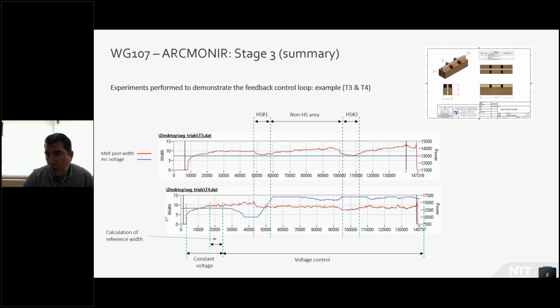However, if we introduce the voltage control and the closed loop control system for the arc voltage, we can see that in the area where the first heatsink starts, the melt pool goes to around the initial value here, which is around 9.5 millimeters. And then we can see that during the whole rest of the process, the melt pool is quite constant. And when we get to the second heatsink, it goes down a little bit again, but not as much as it did in the non-controlled process. And then the melt pool remains again around the initial value.